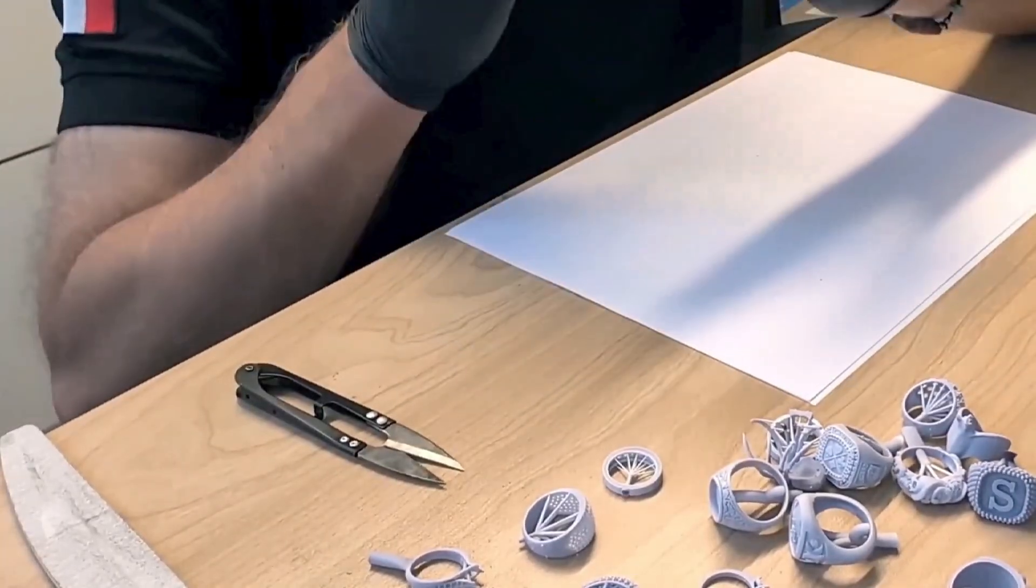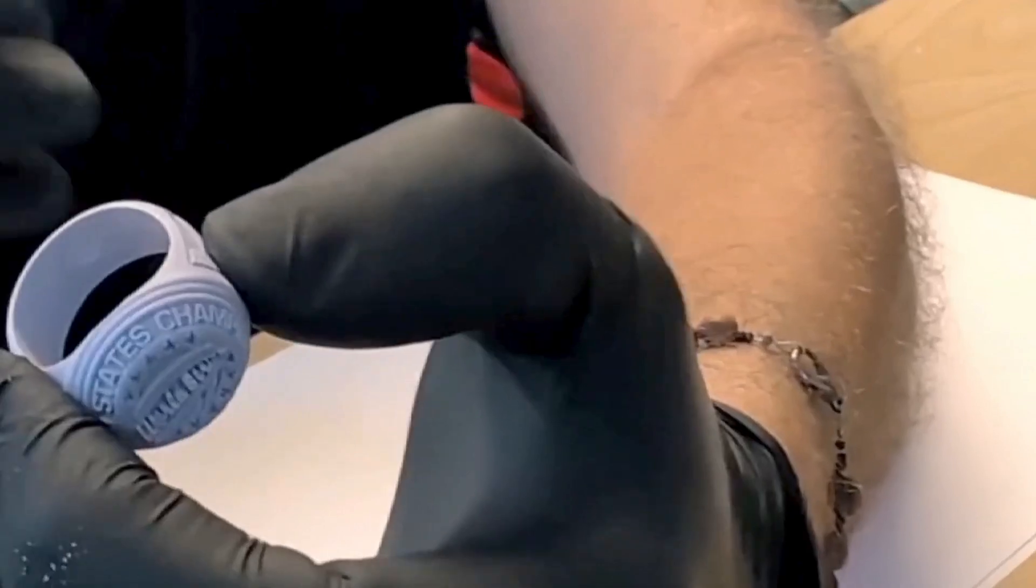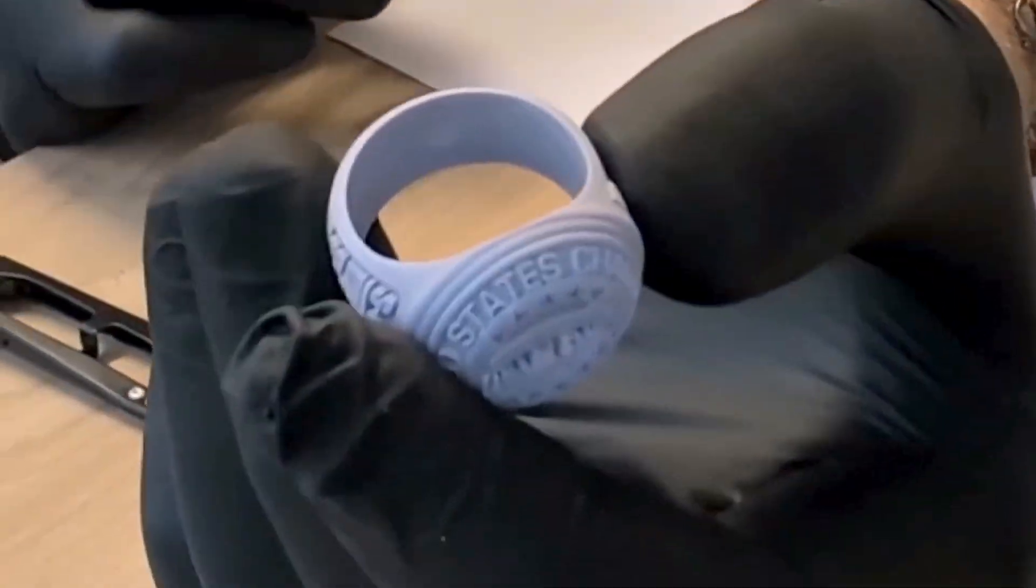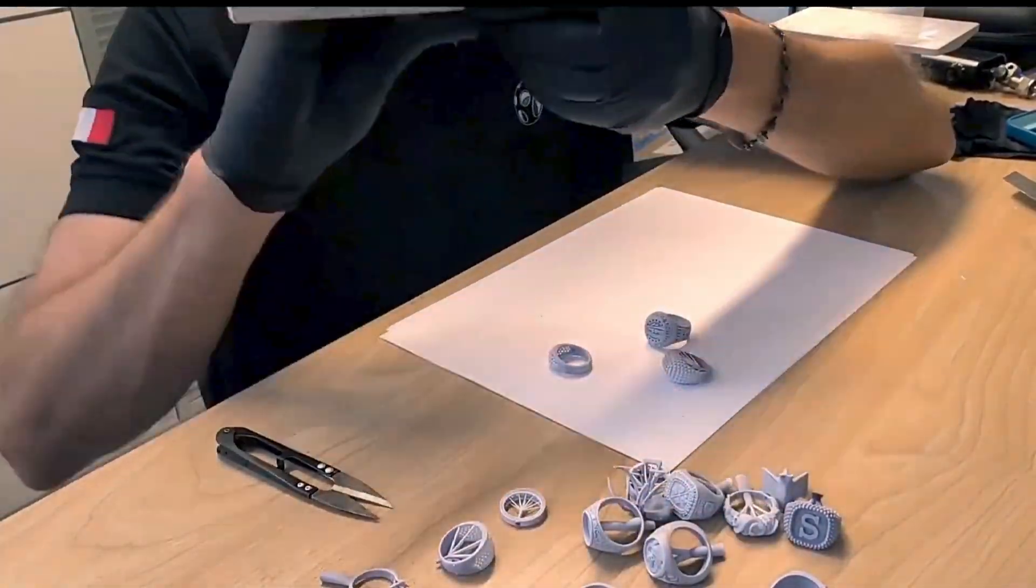For this commemorative ring, I believe an auxiliary channel is necessary for correct metal flow. The sprues are positioned so that they don't damage the models, but most importantly, so that their removal is easy once the casting is done. According to the model mass, I will select the sprue size and number.